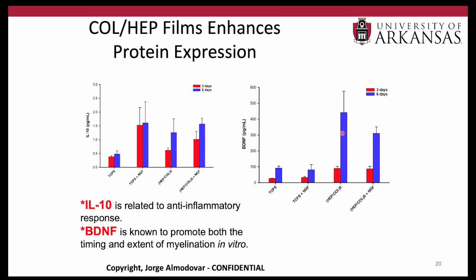And what we saw, very interestingly, is that the expression of BDNF increases drastically when our coatings are present. We saw that both at 3 days and even more so after 6 days of culture. Drastic increase of that protein expression, and that's really good. That tells us that the cells on our surfaces are in a state of repair, that they want to repair, they want to secrete all of these factors and promote nerve regeneration.